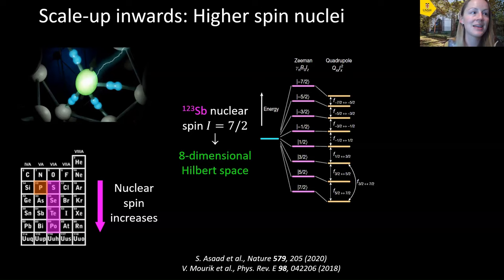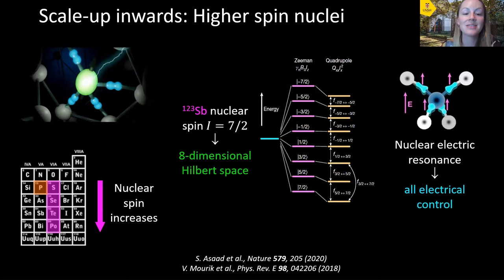So the frequency splittings are all slightly different. So we would be able to individually address these levels. And so we could look at operating a qudit instead of just a qubit, where the d is like a higher dimensional system. And this has nice implications for error correction, or you could use the system as multiple qubits. And another nice thing about these high spin donor nuclei is that they have something called a quadrupole moment, which allows us the exciting possibility of using all electrical control of the spin of the nucleus. Because when you apply an electric field to the system, it distorts the charge distribution around the nucleus and drives something called nuclear electric resonance, which would allow for smaller electrical antennas to be used for our devices instead of the current large on-chip microwave antennas that we use for magnetic drive at the moment.